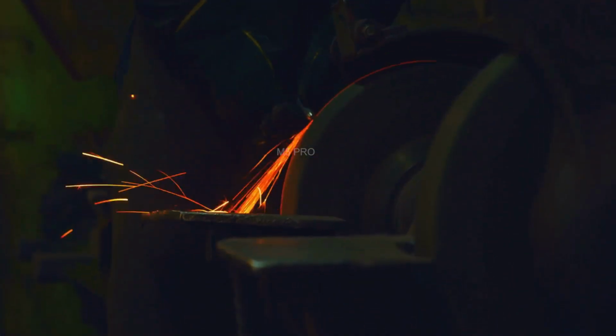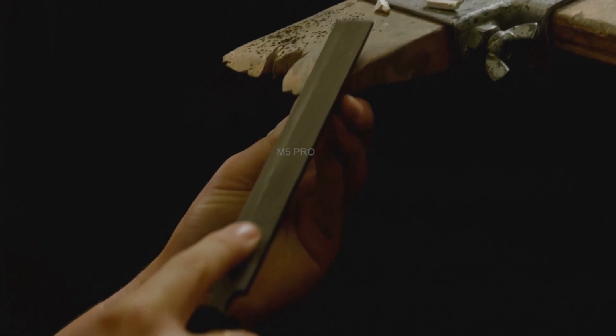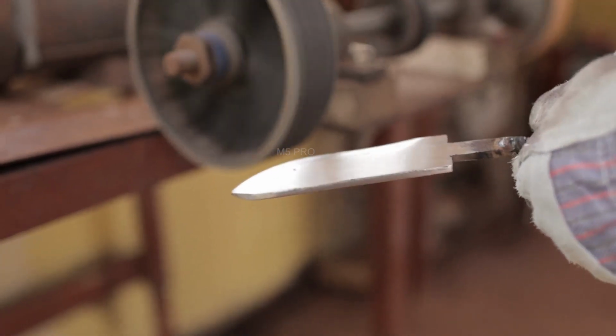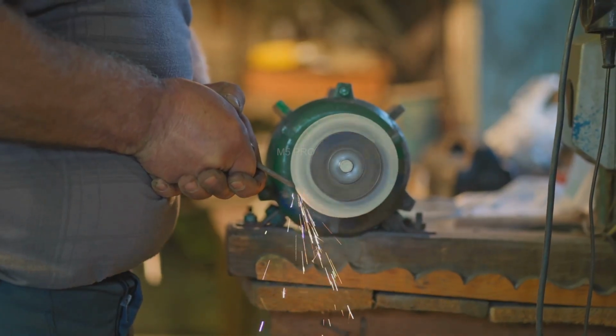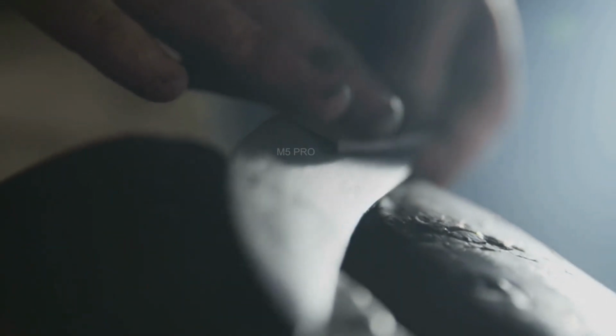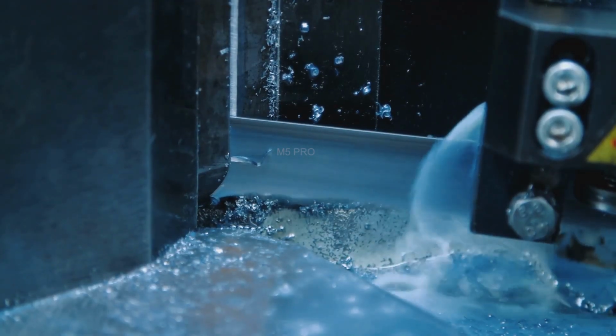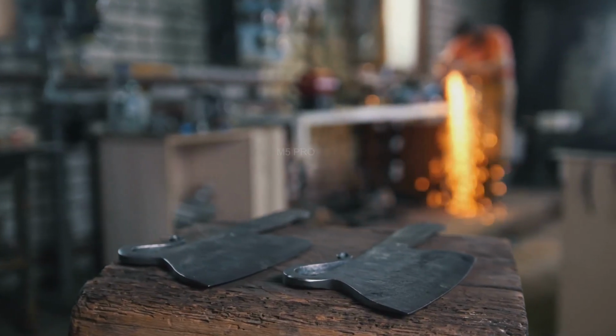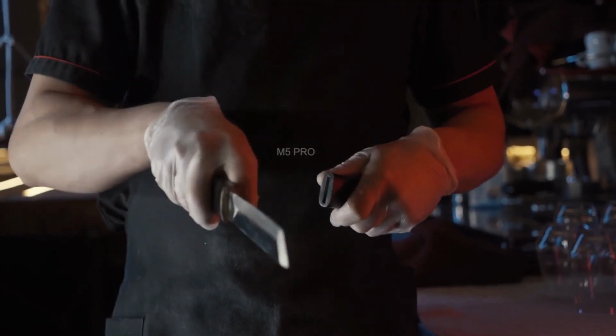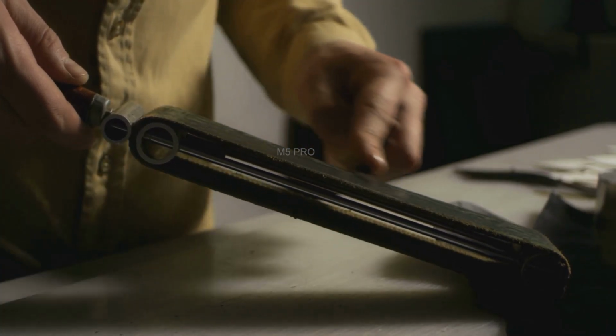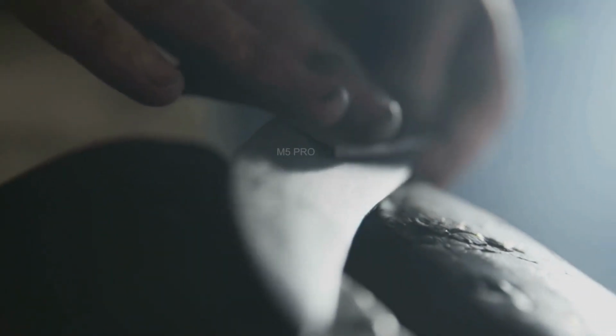The sharpening process often begins on a slow-moving, water-cooled grinding wheel, or a specialized belt grinder with a very fine abrasive. An operator holds the blade at a precise angle against the moving abrasive. Maintaining that exact angle along the entire length, from the heel to the tip, is crucial. Jigs and guides can be used, but the final touch often comes from hands-on experience. The water bath keeps the edge cool to prevent softening. After grinding, the edge is honed to refine it further. Honing is done on an even finer abrasive, like a ceramic rod or a leather strop with polishing compound. This removes the microscopic burr, a tiny ragged flap created during grinding.